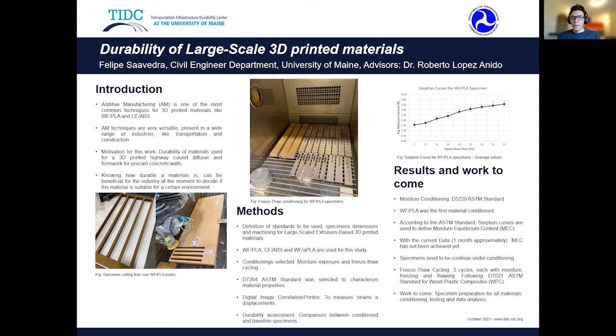About the other conditioning, freeze-thaw cycling, the one selected followed the ASTM D7031 standard for wood plastic composites. Each cycle goes through three states. The first is moisture, then freezing, and then thawing. This was already completed also for wood flour PLA, so the next step is to test the specimens.